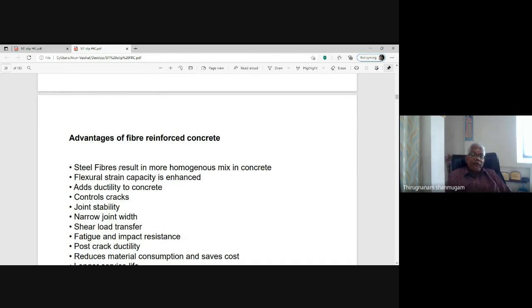So normally in fiber reinforced concrete, the volume fraction of the fibers, steel fiber, is limited to 1%. The optimum volume fraction of the fiber is about 1%. You need not provide 1.5 or 2% fibers, etc., because it will not contribute to the improvement in the strength and durability properties.